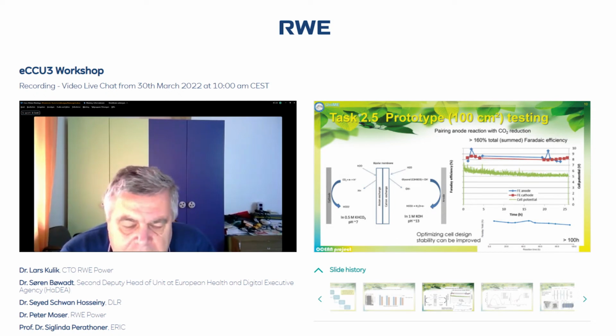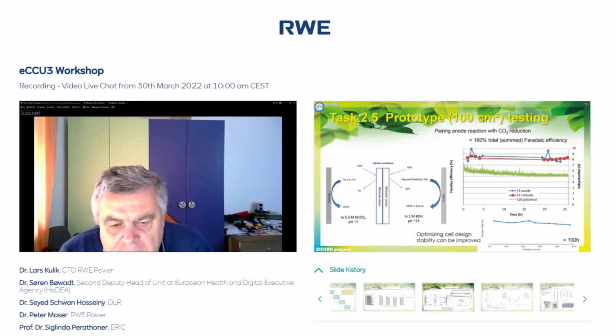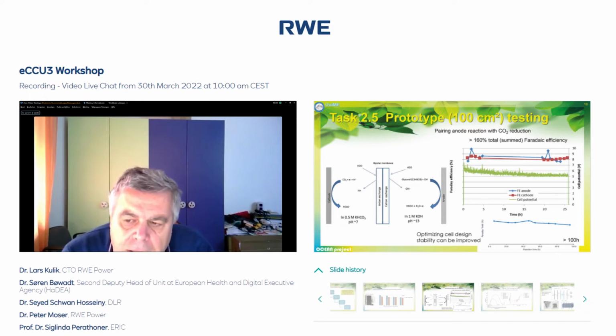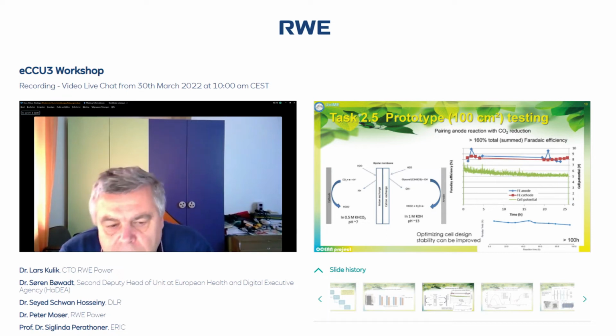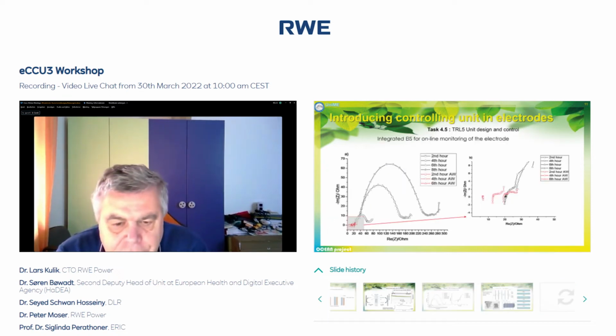Here we see some of the results of the system. You see the two paired reactions. We are forming exactly the same product at the end on the two sides, but of course we are starting from different feeds: CO2 on the cathodic side, and glycerol on the anodic side. We also have a really good and stable performance for over 100 hours. Formally, the total Faraday efficiency summed is more than 160%, which is the sum of the cathodic and anodic reactions.